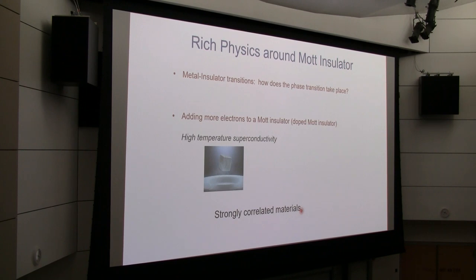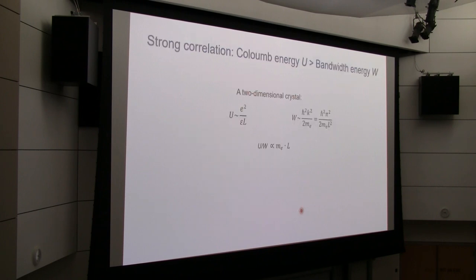So if we think about the Mott insulator and describe it a little bit more mathematically, what it says is you have very strong correlation when the Coulomb energy, U, becomes comparable or larger than the bandwidth energy of the electrons. And when you write it in the formula, we know the Coulomb potential is roughly defined as e squared over the electron separation, which is characterized by the lattice size L and modified by dielectric constant epsilon.